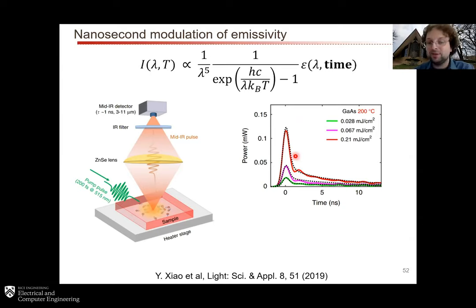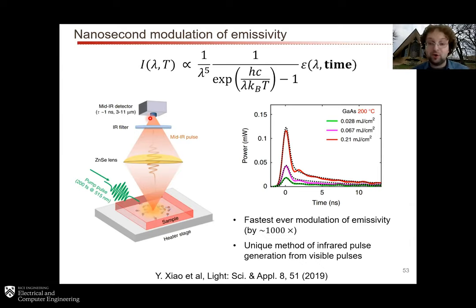So in this case, you're actually measuring not only an emissivity modulation, but also a temperature modulation due to hot carriers in the sample. But nevertheless, we actually do see both effects, and we can model them very well. These dotted lines are a model that we put together that takes into account essentially carrier generation as a function of depth, the temperature as a function of depth, changes in optical properties as a function of depth, and as a result, what the overall thermal emission as a function of time is. We're also able to calculate the spectrum, although I'm not showing that here.